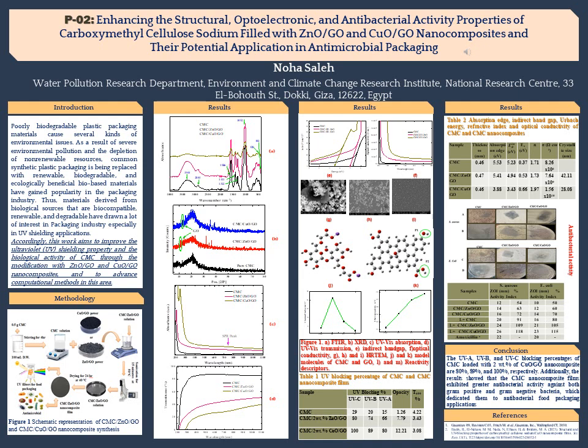Scanning electron microscopy and energy dispersive X-ray spectroscopy analysis confirmed the dispersion of zinc oxide, graphene oxide and copper oxide, graphene oxide within the CMC matrix. This indicates that the CMC nanocomposites have promising applications in packaging materials. These results were confirmed by the quantum mechanical calculations utilizing density functional theory.